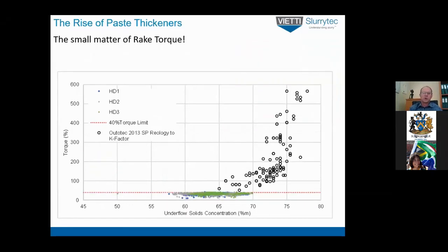At the same time, some work was done by Outotec on a small pilot-scale thickener, which showed that they could get higher densities and achieve their design density, but you would have to have much higher rake torques to achieve it. And in fact, for the 70, you were talking about running continuously at 100%. So the calculation is correct, but it's the application in the field. So what ultimately we have to do is look at bigger torques for these central drive paste thickeners.